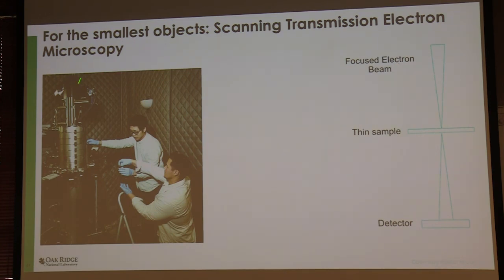The accelerators that we use to send the electrons through materials have exponentially grown in their ability to focus those accelerated electrons. They can actually focus those electrons down to an angstrom now, and they can accelerate the electrons up to several hundred kilovolts. So they can do some really neat stuff if you throw those electrons through a thin film and have a detector. The other thing that's improved is that they can control where they focus them very precisely. We can raster those samples to single angstrom levels on demand.